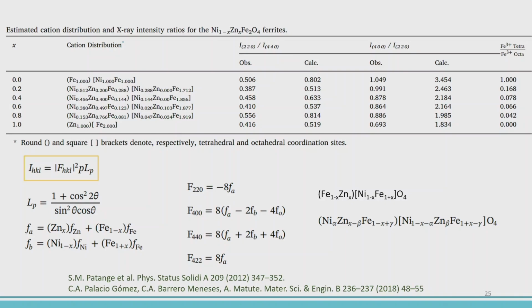Look, this is another way with X-ray diffraction. There are 2 ways for the cationic distribution. This is using the intensities of the lines, but not all the lines, specific ones with some Miller indices that are very sensitive to the cationic distribution in tetrahedral and octahedral, and we can use this formula.